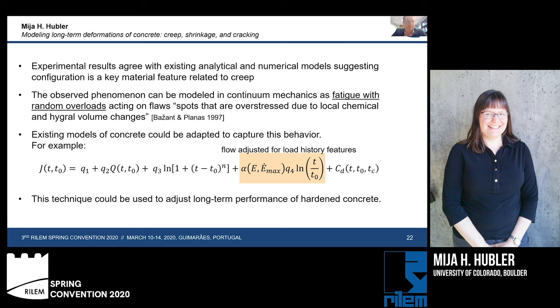Okay, so these experimental results, or the responses that we see from these experimental results, actually tend to agree with what existing analytical and numerical models are suggesting. In fact, that the configuration of our material is key to describing the creep in long-term behavior. The observed phenomena could also be modeled not on a small scale, but on a continuum mechanics scale as fatigue with random overloads that are acting on the flaws of our material. If we look at existing models of concrete, this type of behavior could also be adapted.